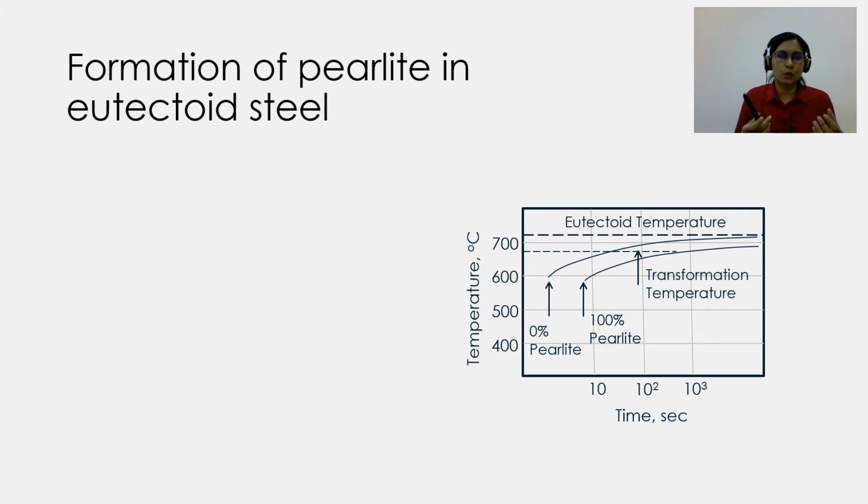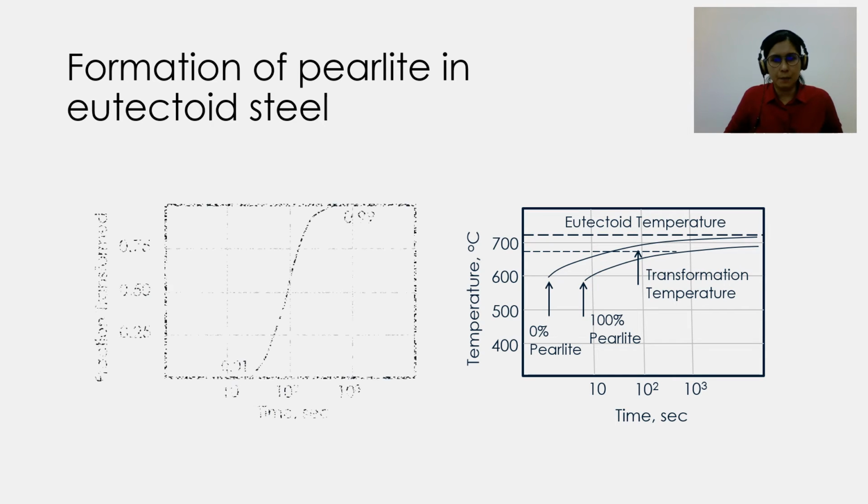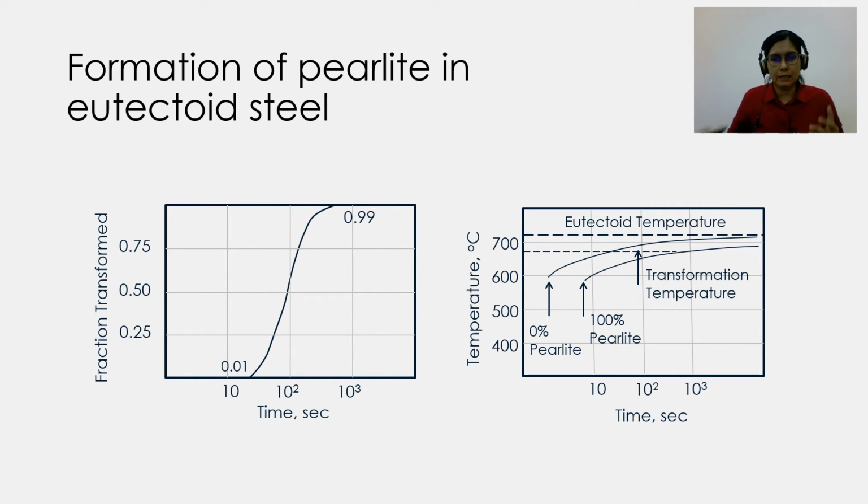So you want to end up with a microstructure of coarse pearlite, for example. So using the TTT diagram, we can design the procedure on how we want to conduct this heat treatment. So for this example, we know that just by looking at the TTT diagram, we can quench to a certain temperature where we will end up with coarse pearlite.